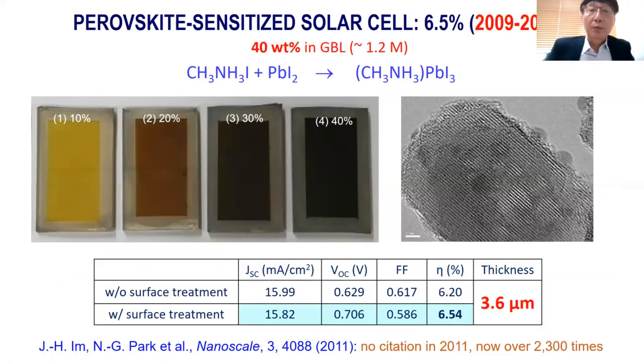Coming back after the 2007 Nano Euro conference, I studied the perovskite solar cell, and in 2011 we reported a perovskite-sensitized solar cell showing 6.5% efficiency. We provided an excellent recipe to form stable methylammonium lead iodide by optimizing the concentration of the precursor solution. Shown here is the quantum dot morphology, with the perovskite sitting on titanium oxide, and the film thickness is much lower than Miyasaka's film thickness of about 8 micrometers.